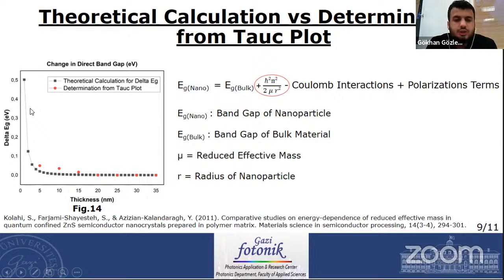In thin films, charge carriers move freely in two dimensions, but in the third dimension, which is nanometric, they have very limited movement and are confined. In this study, it has also been observed that with increasing thickness of the semiconductor thin films, the amount of shift towards the blue region is reduced, which indicates the movement of charge carriers is freer, and thus the quantum confinement effect is reduced. Also, I want to say that in this relation, we just use the first term, because the second and third terms are ignored compared to the first term, because the dominant term is the first.